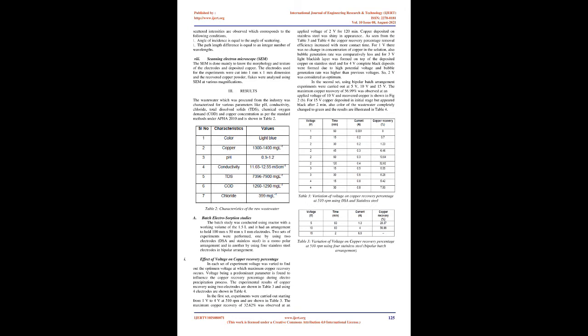0.1 ml and 1 ml of 1000 mg/L Cu stock solution was pipetted into a 100 ml standard flask and Millipore distilled water was used to make up the solution to 100 ml. These solutions were used to calibrate the instrument. Later, a complete elemental analysis was carried out over a period of 30 seconds by injecting 0.5 ml of wastewater sample with a wavelength of 324.7 nm. pH. Standardization of the pH meter was done by using standard buffer solutions of pH 4, 7, and 9.2.